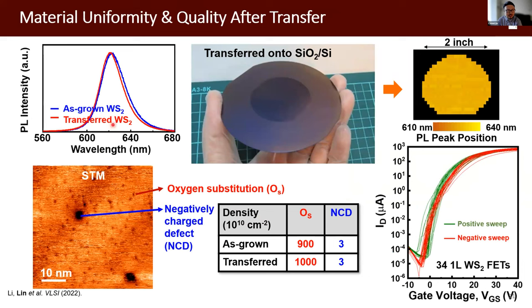Here are some material characterizations from the photoluminescence before and after transfer. And in the mapping, we can see the material was intact after transfer. And with the STM measurement, we can count the defect density before and after transfer. So they show similar levels of defect density, which means the transfer approach does not introduce any actual defect. And we also have device measurements to show the device performance is consistent across the wafer, and there isn't any hysteresis, which also indicates the interface and defects are very good.